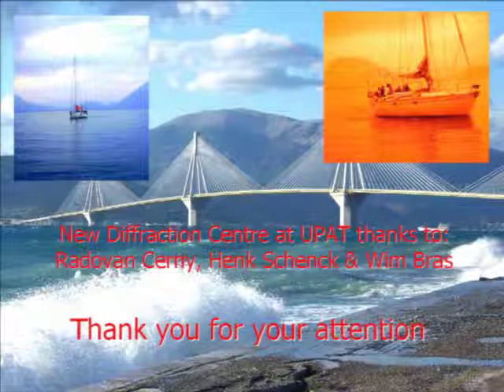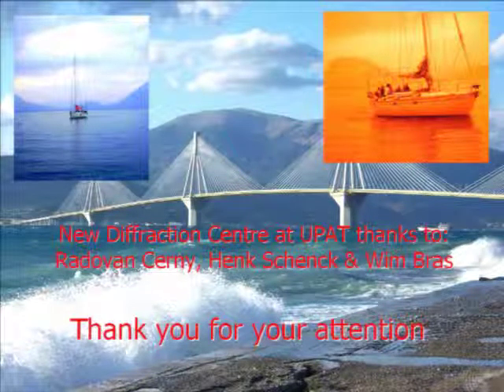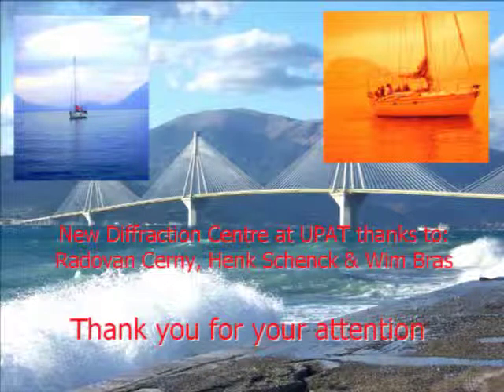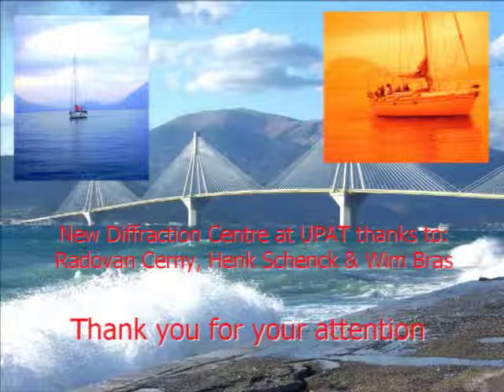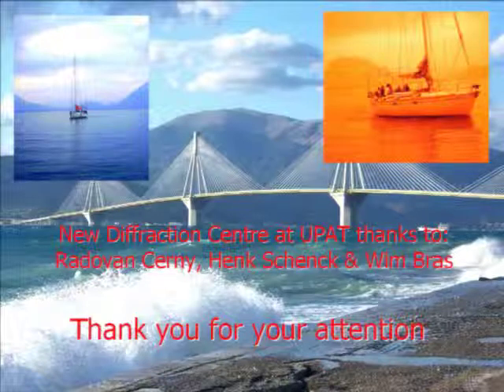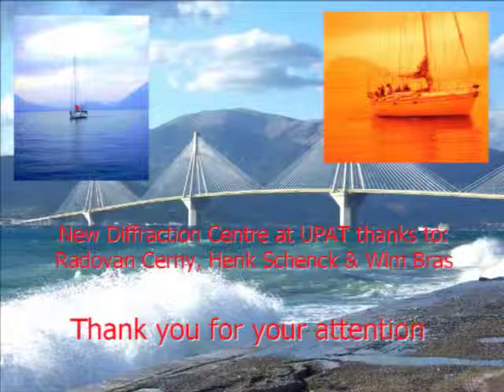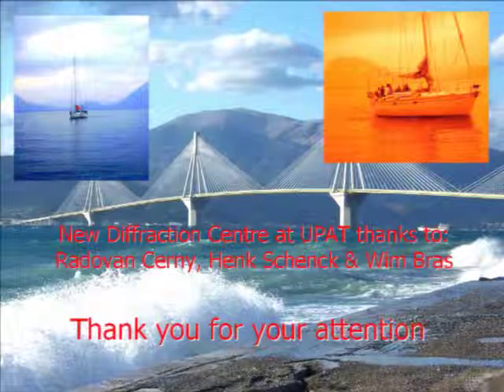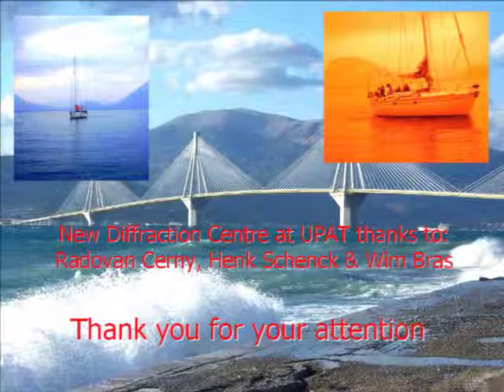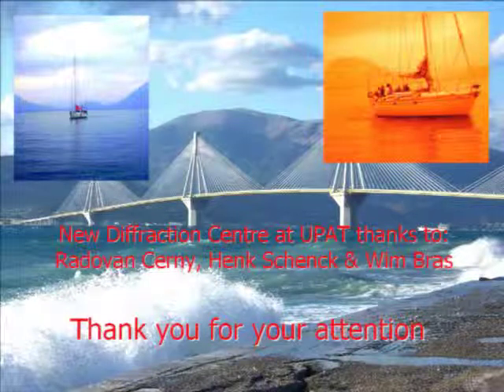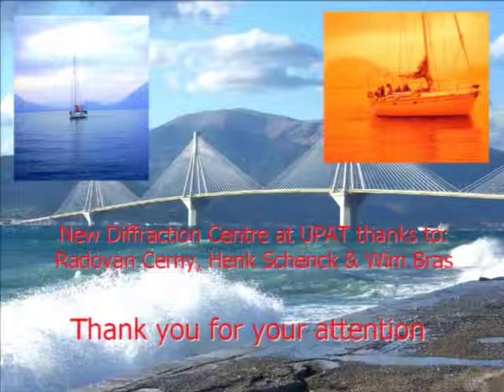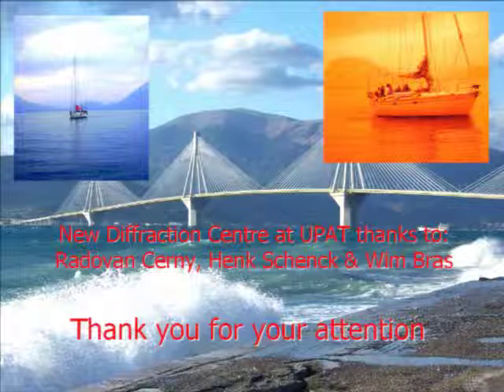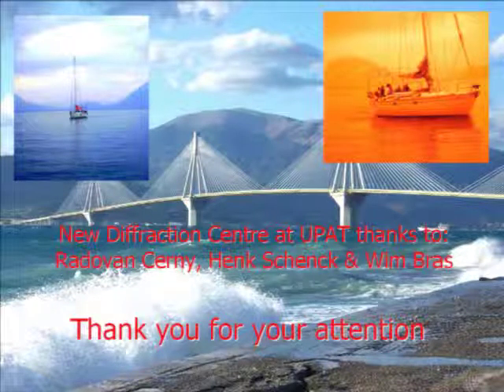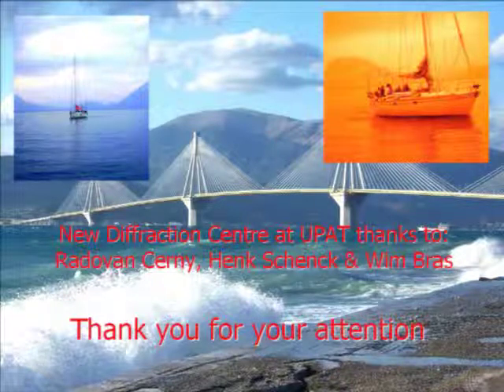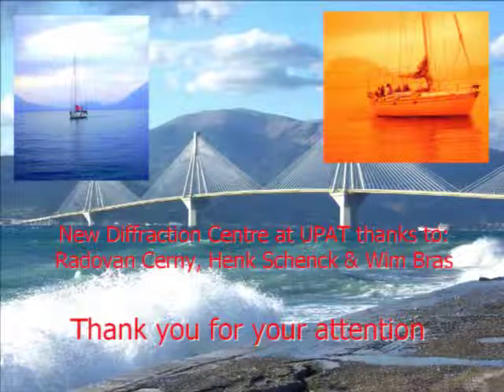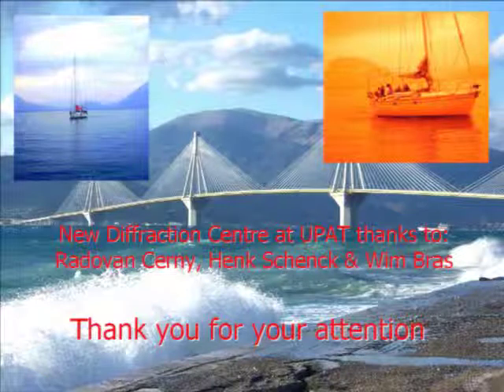Both enthusiastic and skeptical, after 10 years, because it's been now 10 years that we are trying to do that, much longer. So they start thinking that they can get some structural information, even if not the complete structure. For example, our lattice parameters are much more accurate because we get the whole profile in a shot. And that's something that they got to understand. And we had to say, but you tune your beamlines by using silicon powder in order to calibrate the wavelength. So one would expect that they would have got that, no? So they trust lattice parameters up to a certain point, space groups, and maybe the molecular replacement they can accept. The structure refinement, they start being a little bit afraid.